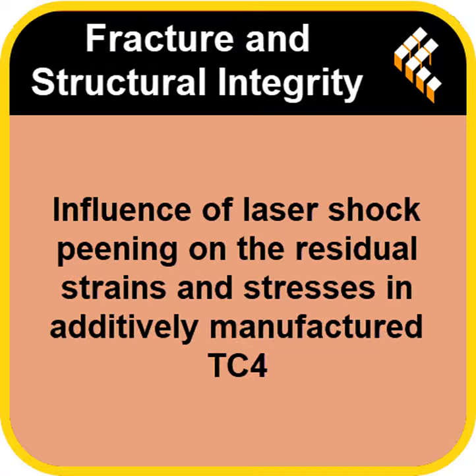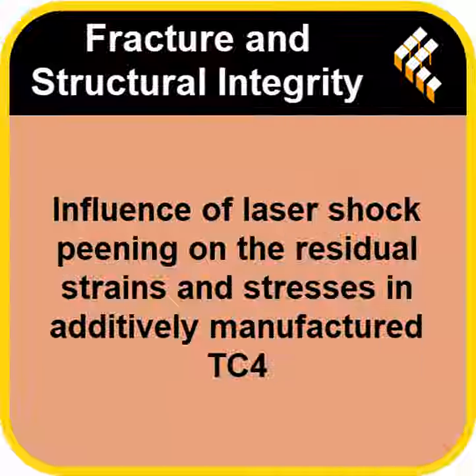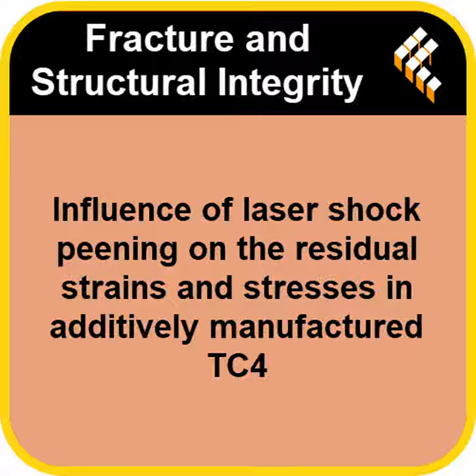It forces that plastic deformation you mentioned. Exactly. And that deformation is what introduces those beneficial compressive residual stresses deep into the surface layer. So we're swapping out the bad pulling stress for the good squeezing stress, which should make the part tougher, more resistant to fatigue. Correct. And importantly, because the laser interaction is so brief, nanoseconds long and confined, you get very little overall heating compared to something like heat treatment.